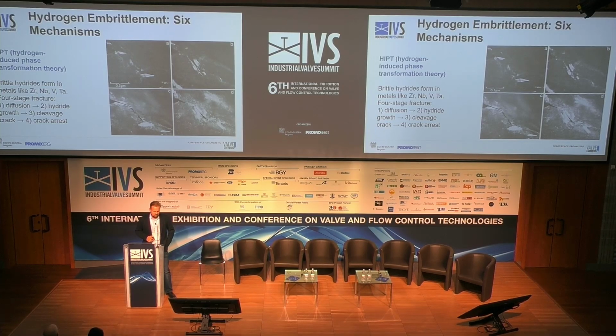Another theory is what they call HIPT, the hydrogen-induced phase transformation theory, and this is a particular mechanism that is bound to only some kinds of metals. In this case, zirconium, niobium, vanadium, and tantalum. Those metals, as we say in catalytic chemistry, are more active, more prone to activate hydrogen and split it into active species and make it reactive on top of the surface. What happens here is that you have 4 different steps. Those steps sometimes occur over a very long time, sometimes in split seconds. That's what makes this not very dangerous, but very unpredictable. And we need to keep an eye on that.